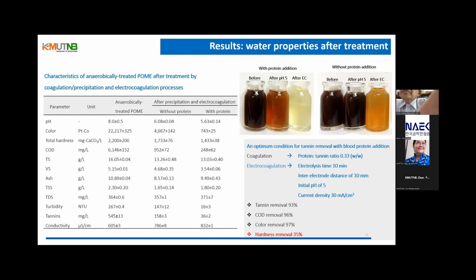This table shows the property of the effluent after the treatment by the precipitation and electrocoagulation using the optimum condition of pH 5, current density of 30 milliamp per square centimeter, and inter-electrode distance of 10 millimeter. After tannin precipitation in series with the electrocoagulation, the COD decreased from above 20,000 milligram per liter to about 700 milligram per liter with the addition of blood protein.